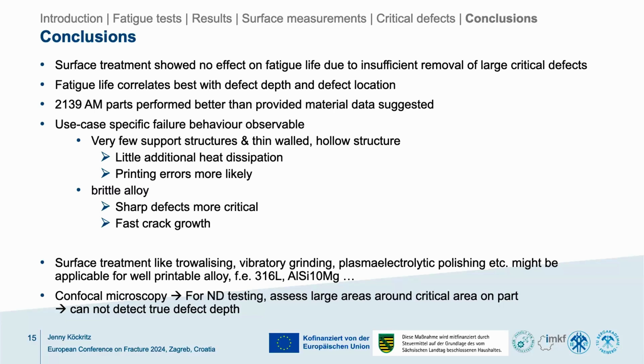We did observe some use case specific failure behavior. So due to the thin walled hollow structure, we didn't need a lot of support, which is actually pretty good if you look at additive manufacturing. However, this also meant that we didn't have good heat dissipation here, and printing errors were more likely. Also, this 2139 alloy is very brittle. So we could observe sudden crack growth, and also sharp defects might be more critical, well, will be much more critical here, even if they're small.